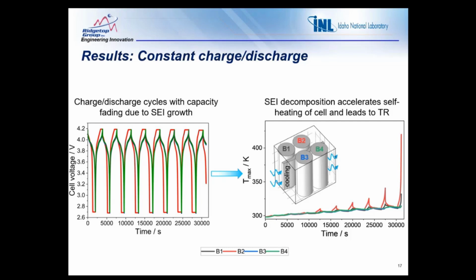Over time, we observe capacity fading due to the growth of the SEI layer on the anode. This layer forms during cycling and consumes active lithium, reducing the battery's capacity. The fading trends are evident as the charge discharge profiles decrease in amplitude with each cycle. And just to note that we have considered the degradation of battery mostly in battery B2, that is shown in red color, and that's why we see more capacity fading in battery B2 compared to the other ones.